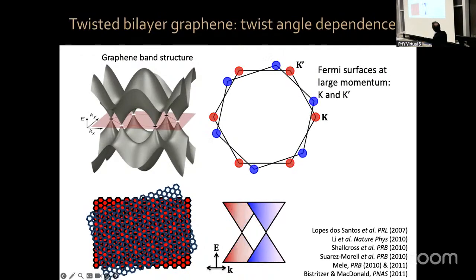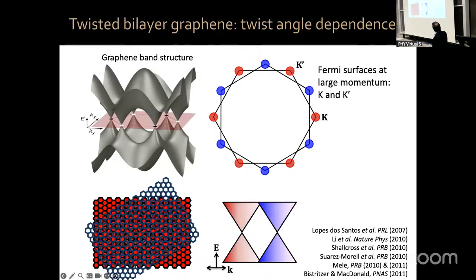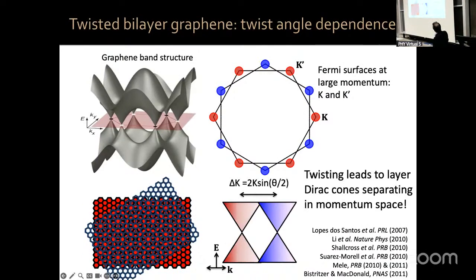So rotation leads to a separation, in particular of these Dirac cones. Twisting leads to layered Dirac cones separating in momentum space, and they separate by a distance proportional to the sine of half the twist angle. So if you rotate by a small theta, this separation is proportional to the twist angle.